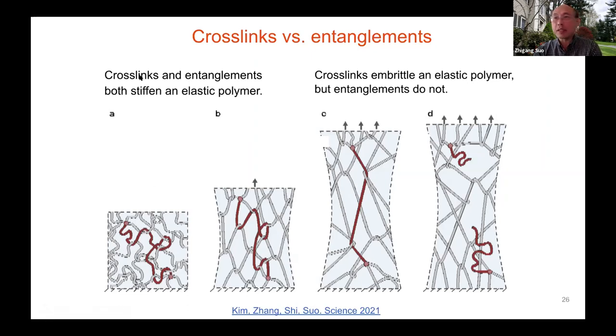So here's a summary of the basic insight. Crosslinks and entanglements both stiffen an elastic polymer. If you just stretch it, the entanglement and the crosslink function almost the same way. They stiffen the material. However, here's another insight. Crosslinks embrittle an elastomer, as we just said. If you make a lot of crosslinks, the chains become short and your toughness goes down. However, entanglements do not embrittle the material.